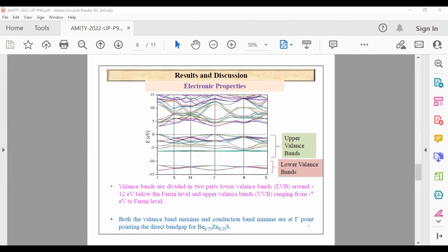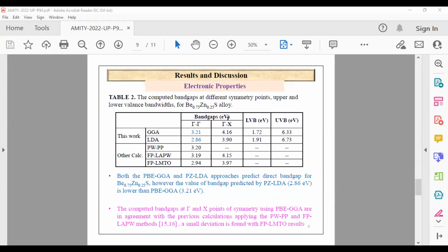The first feature we can see is that both the conduction band minima and valence band maxima are at the gamma point. So our calculation predicts this is a direct band gap semiconductor. When we talk about the band gaps calculated at other points, at gamma to gamma there is a band gap of 3.21 by GGA calculation, and by LDA calculation we obtained a band gap value of 2.86. So GGA predicts a larger band gap than LDA calculation.